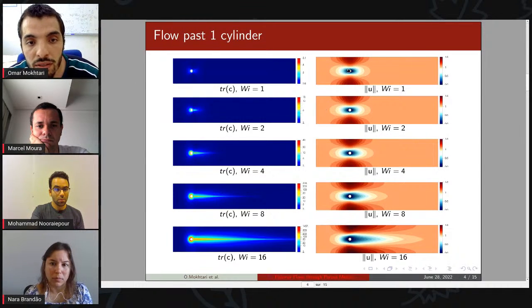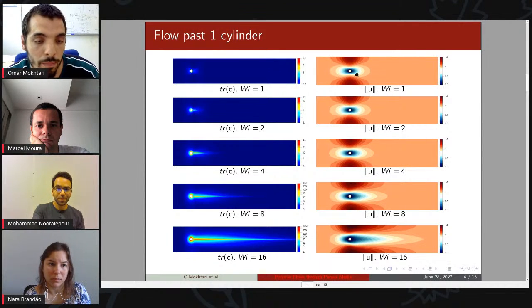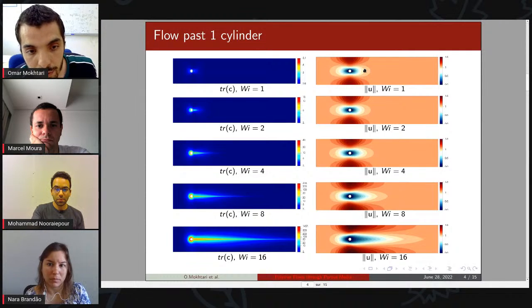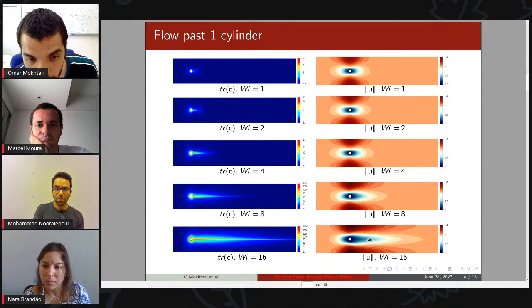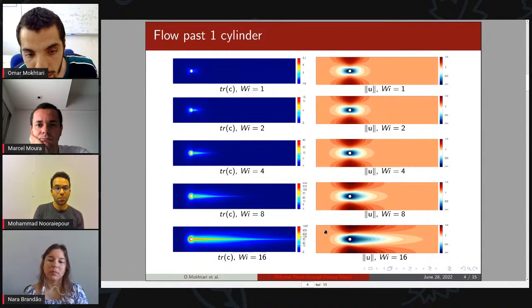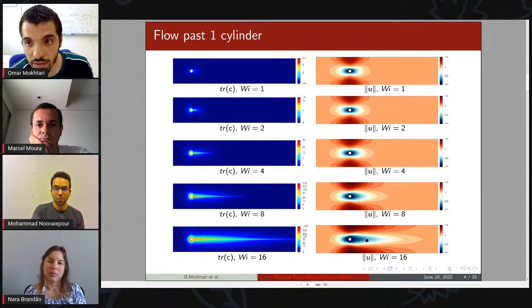So if we consider the velocity field, for a low value of the Weissenberg number, we have a Stokes flow with fore-aft symmetry, and by increasing the Weissenberg number, we can see a decrease in velocity in the wake of the cylinder due to the strands, and by conservation, we have an acceleration of the flow around the cylinder.